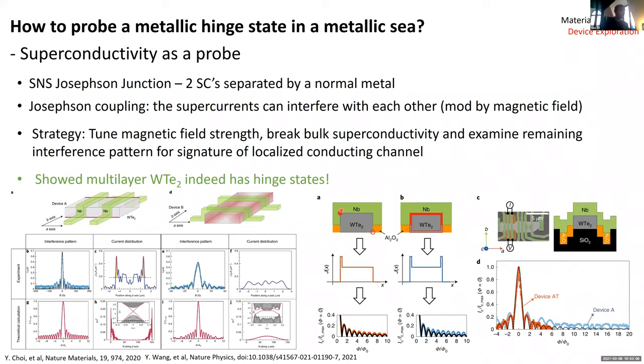So we tried it. And sure enough, we found that in this type of device, of course we did a lot, you return back to the expected Fraunhofer diffraction pattern without the SQUID. So you only see the SQUID pattern when you connect to both the top and bottom. In this way, we were able to tell the difference between the hinges and the edges, and confirm that WTe2 does appear to have these hinge states.